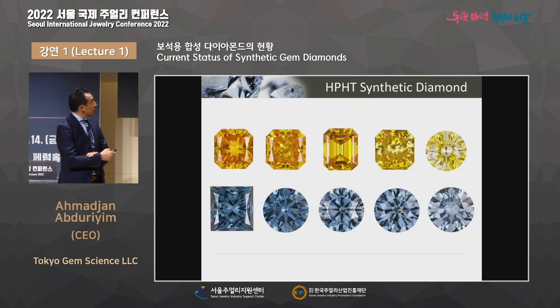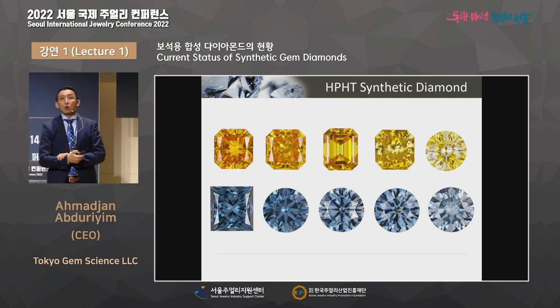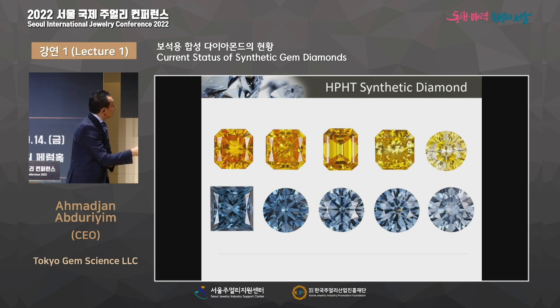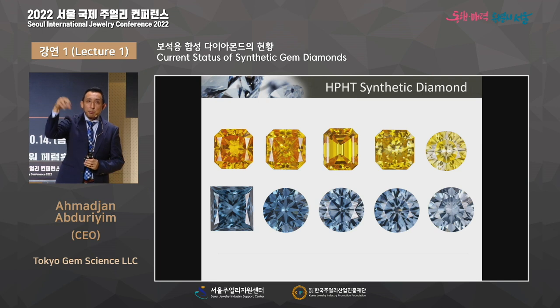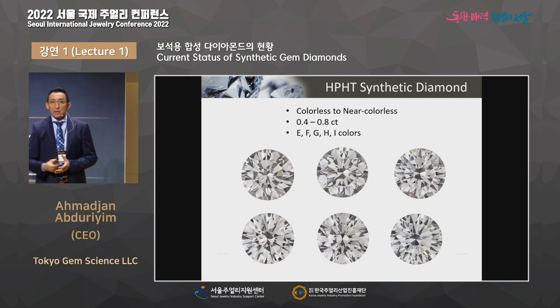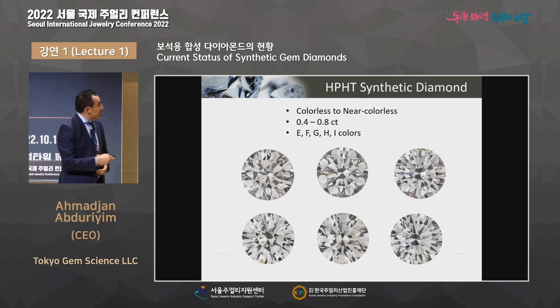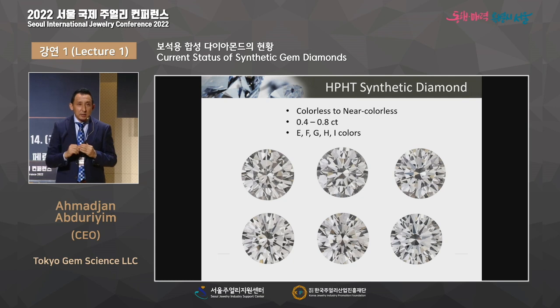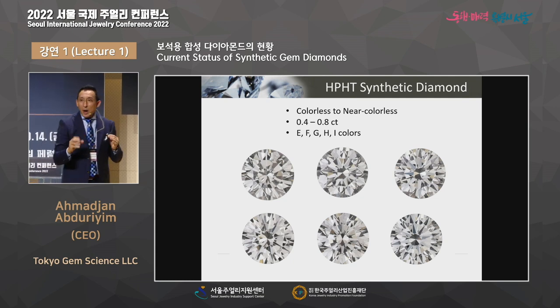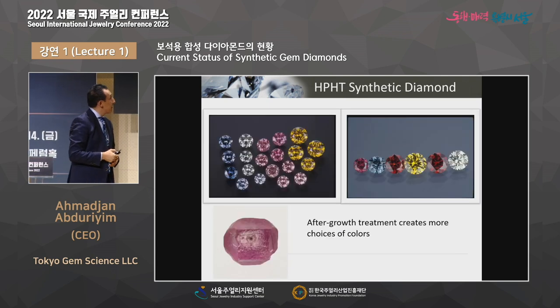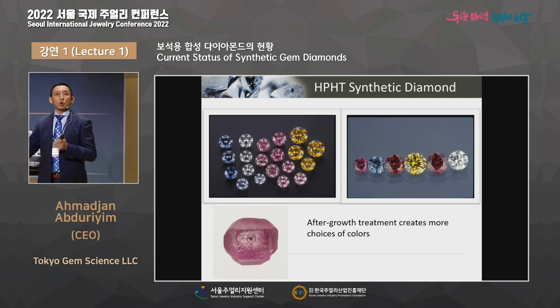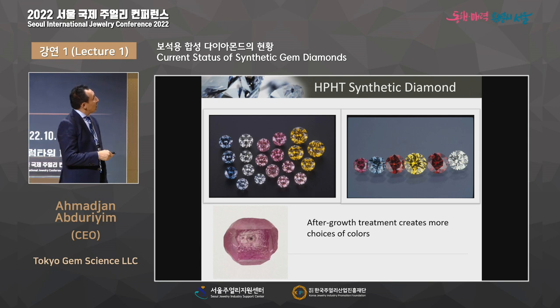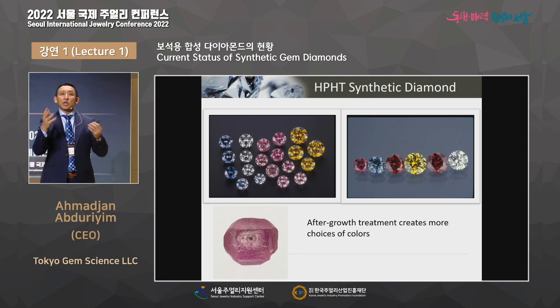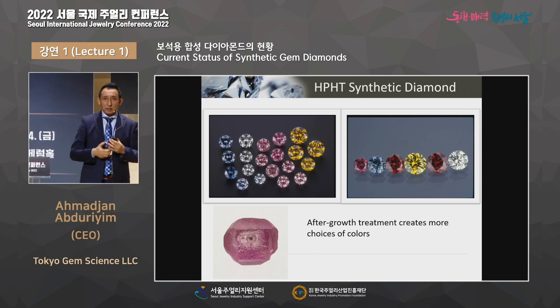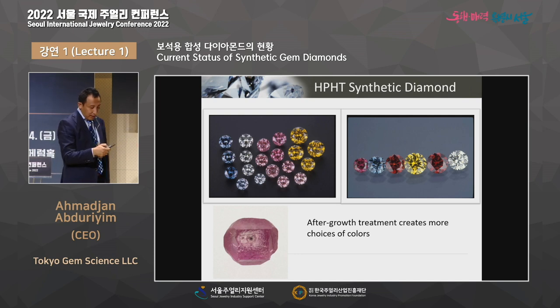So you see the synthetic diamond, they can make a very fancy yellow color, fancy orange color, and this is a synthetic blue diamond. They intentionally dope boron inside to make blue, like the Hope Diamond in the natural. And they can also make colorless, but it takes 1 month to create colorless because the growth rate is very slow. The yellow one is faster, like 1 week. And they try to make a color similar to natural diamond. However, to create pink or other colors, they need more treatment, like irradiation and heat annealing after the growth process, to make all the fancy colors like this.